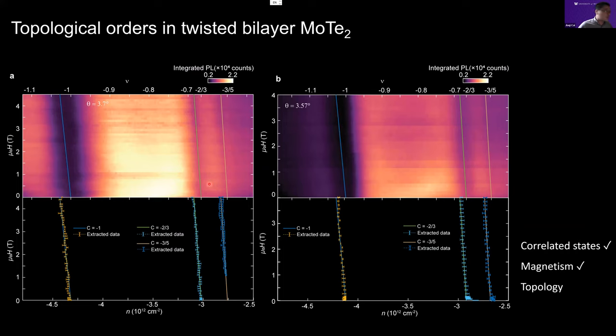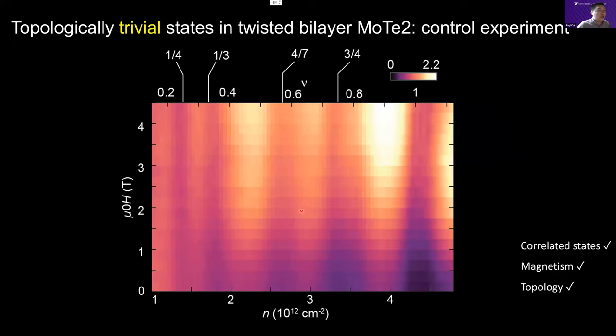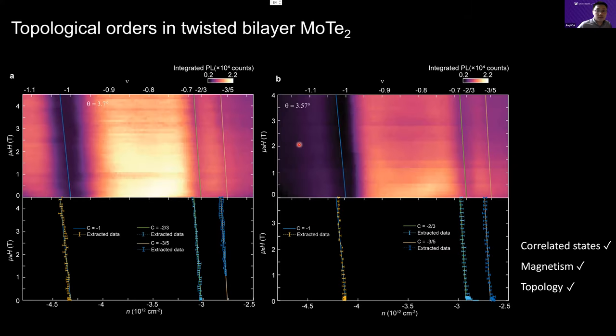We also see in the fractional states a fractionalized Chern number, and we also see another fractional state. We can very well repeat this measurement at another beam spot of the sample. So now we have established that there is non-trivial topology in the system, but we need to do a sanity check. What if this effect actually comes from some trivial reason of shifting? So we can do the same experiment on the electron side, with respect to the magnetic field, and you can see there is no dispersion at all. That gives us confidence to say, okay, this probe actually works pretty well.